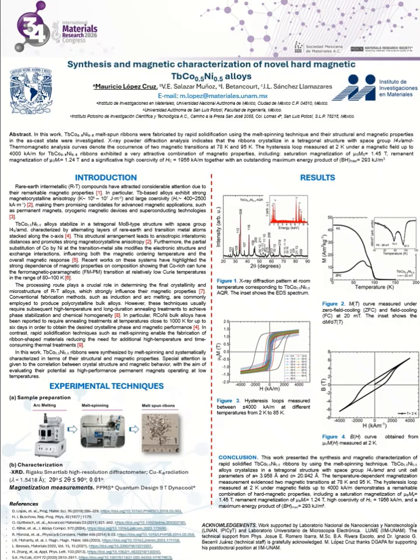Now I'm going to present the results of this project. In figure 1, we have the X-ray diffraction patterns measured at room temperature. The diffraction peaks indicate that these alloys crystallize in the tetragonal structure. In figure 2, we can see the thermomagnetic curves measured under an applied magnetic field of 20 millitesla. The curve reveals the occurrence of two magnetic transitions at 78 Kelvin and 95 Kelvin, which are further confirmed by the minimum of the derivative curve shown in the inset of the same figure.